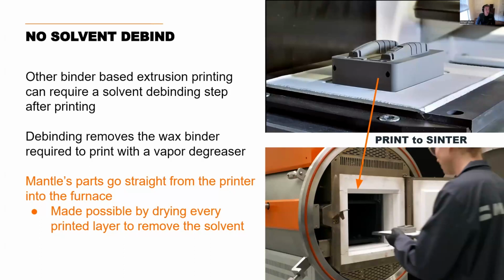separate solvent debinding step, eliminating the need of bringing in those debinding fluids, those systems, and understanding that process. The way that we actually enable that to happen is because every single layer we're drying. So we're removing that solvent that we're also using to flow our material. We're removing it every layer by simply drying it out. We're not printing and then removing it afterwards. Every layer we're removing that solvent. So we're essentially debinding the part in process and removing that solvent right out of the part, rather than having to do this separate immersion solvent debinding step to remove the wax that they use, which is quite different than what we're using in our process.